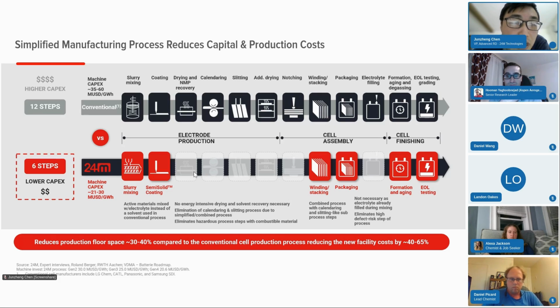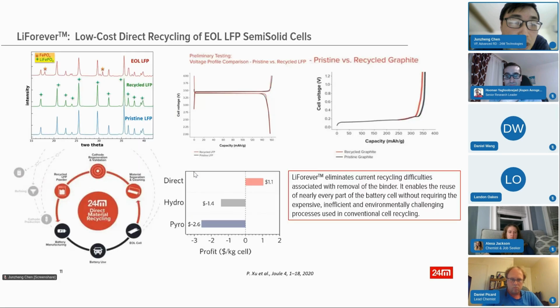Because of that black mass behavior, we are trying to use a method of direct recycling or closed loop recycling of our semi-solid families. What we were doing is we commit cell at the beginning, and we can return back to collect the black mass or end of life cells to wash away most of the inactive component, then the active component, because there's no binder removal process from the beginning to the end. And then the damage to the active material is minimum.